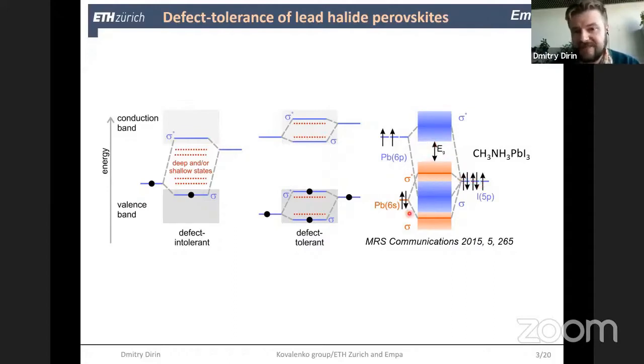dangling bonds of both lead and iodine, or vacancies of lead and iodine, will not create deep trap states. They create only shallow states. And this can explain the very good performance of those materials in all those different fields of research which I have been discussing on the previous slide. Because this means a long lifetime of carriers, and that carriers can have very good mobility. And if we are talking about nanoparticles, it means that surface states, or namely dangling bonds, are not so crucial anymore.